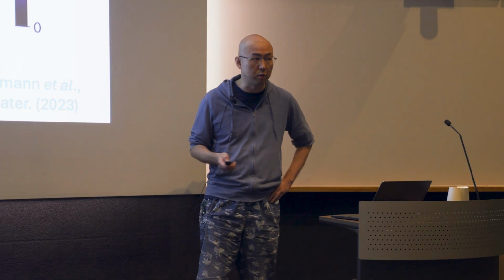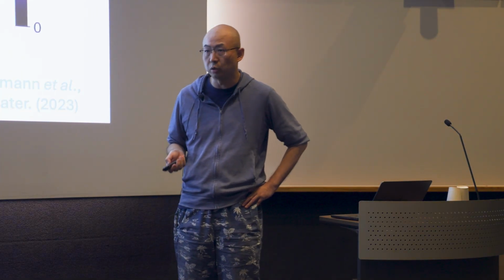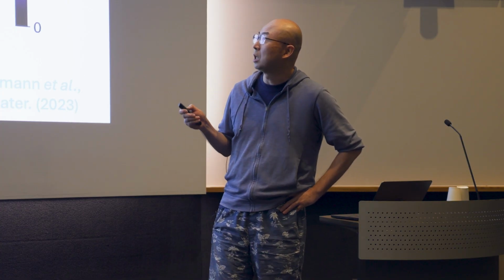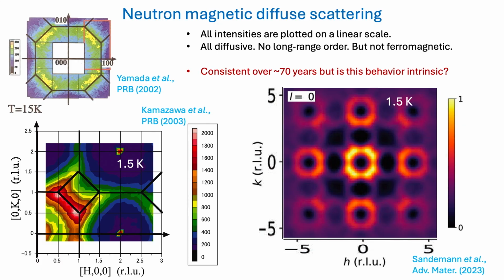Of course, the literature has lots of information already, and you can read through it. The material has been studied by neutron magnetic diffuse scattering in the past. At 15 Kelvin, you have diffusive patterns, which are basically unchanging down to 1.5 Kelvin. So basically, the system has not been changing throughout this temperature region, and it's very diffusive. This data shows no long-range order at all, as we know from the 1950s. So we have consistency over 70 years.